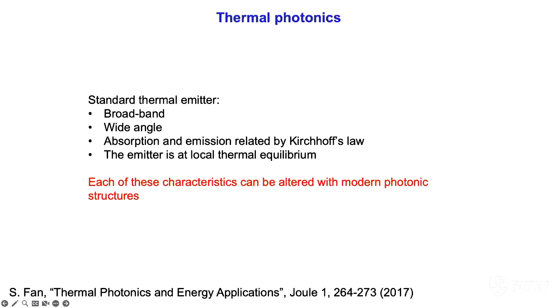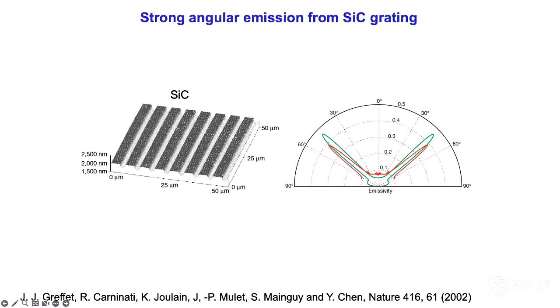And so consequently, that gives rise to a completely new class of thermal radiator that doesn't behave like a standard black body thermal radiator. So I just want to give you a few examples. This is one of the pioneering works by J. J. Greffet. The experiment that he did is to take a piece of silicon carbide and put a grating on that. He basically etched grooves, a periodic array of grooves, into the silicon carbide. When he does that, it turned out that the thermal emission of this structure becomes highly angular. If you heat it up, it emits only along particular directions.